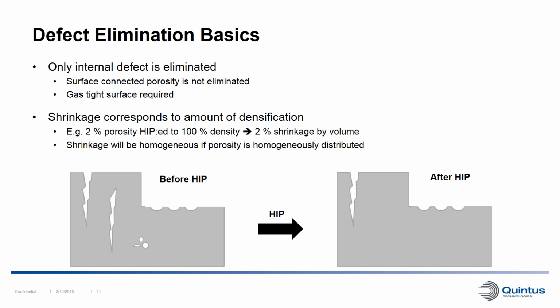This is a misconception that I hear sometimes, that people think that since we have a pressure penetrating the crack, it will open or enlarge during the hip process. But since we have the same pressure acting in the crack as all around the component, there will be no net force to either open the crack or to close the crack.